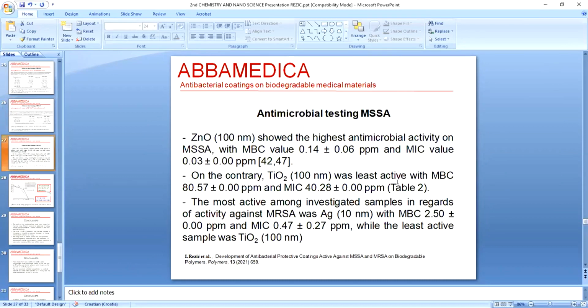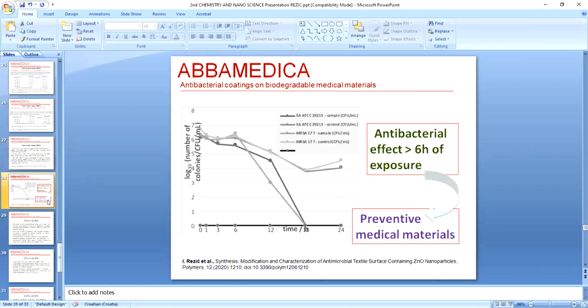Titanium dioxide was least active, but the most active among samples in regards to MRSA was silver nanoparticle of 10 nanometers, while the least active was again titanium dioxide. When we did this time kill methodology, when we wanted to see how many hours need to pass before we have really good antimicrobial effects, we have observed that after 6 hours of exposure, really good antibacterial effect occurs, which means that we have been able to produce surface which is excellent preventive medical materials, which can be used in hospitals for sheets and some textiles.